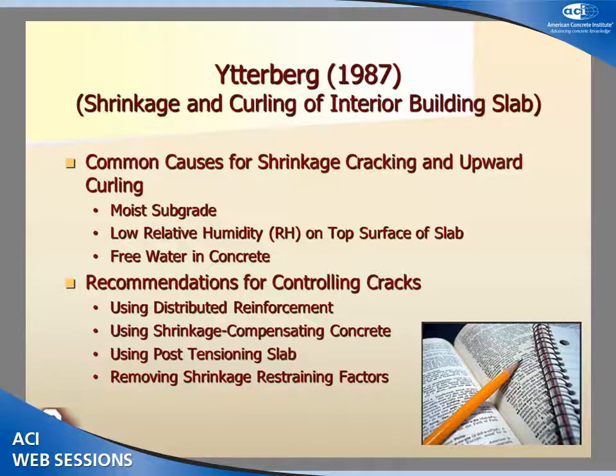In 1987, Ytterberg studied shrinkage and curling, particularly for internal slabs, and based on his study, the common causes of shrinkage, cracking, and upward curling were high relative humidity of the subgrade, low relative humidity of the top surface of the concrete or ambient, and free water in the concrete. So he recommended, in order to minimize these cracks and shrinkage, we should use distributed reinforcement or shrinkage-compensating concrete or post-tensioning slab, or we can remove the factors that restrain the shrinkage.